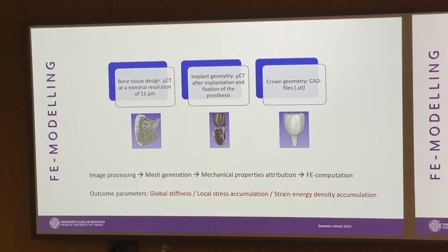The model construction process began by capturing the precise bone geometry of the bony specimen using micro-CT to create the bone tissue design, and in the next step 3 Straumann implants were placed in the specimen following the sequence of 8 mm, 6 mm, and 4 mm from mesial to distal to replace the second premolar and first and second molars. So these positions of the implants were